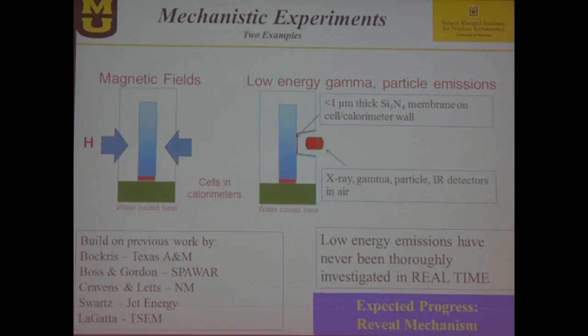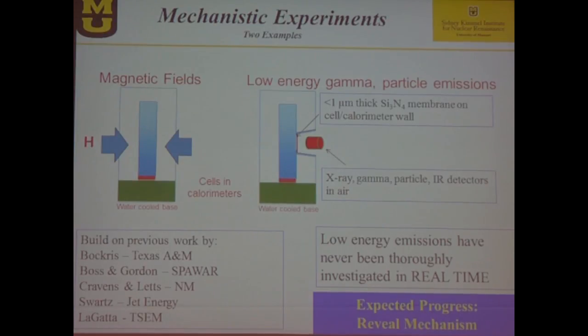that we have found. Now these are experiments that we are suggesting, and some of them we are actually running. You remember the Storms experiment in which the cathode was platinum, the anode was palladium, and there was a co-deposition of palladium on the platinum, and with these experiments we saw excess heat. Small excess heat, but if it is from a nuclear effect, if we put here an X-ray detector or gamma detector or another detector to measure charged particles, or neutron detector, we will be able to see if this is a nuclear source or not.